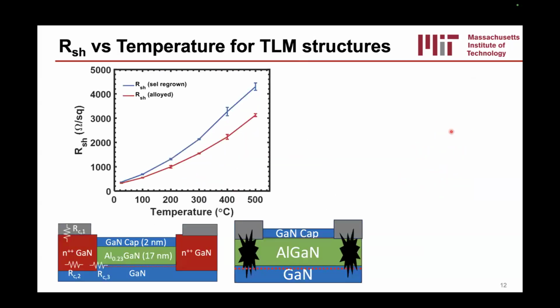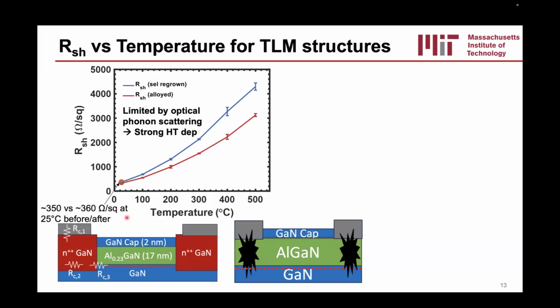We can plot the sheet resistance versus temperature for these two samples and see that at room temperature the sheet resistance is about 350 ohms per square, and at 500 C it increases about 10x to about 4,000 ohms per square. This is due to what I'll show you later, phonon scattering, which has a very strong temperature dependence. Interestingly enough, if we ramp the temperature back down and cool the device and remeasure, we can see that the remeasured points after cooling down are pretty much identical to the points before heating it up. So there's very little device degradation, at least for short-term measurements over the course of a few hours up to 500 degrees Celsius.